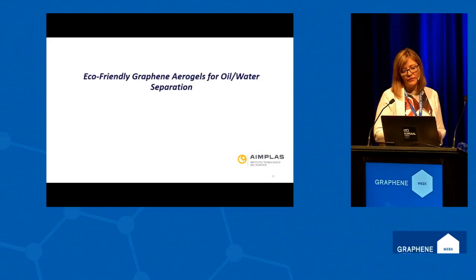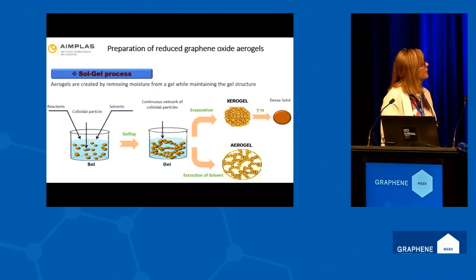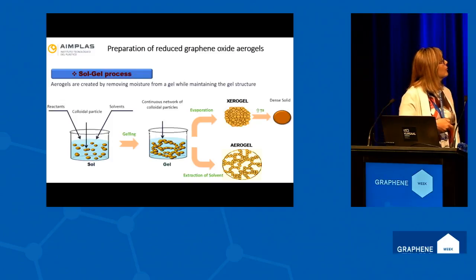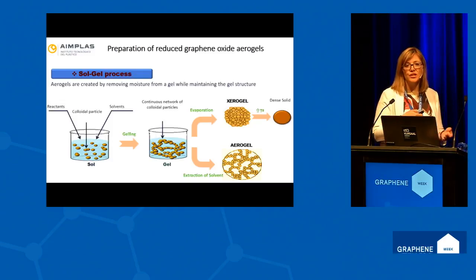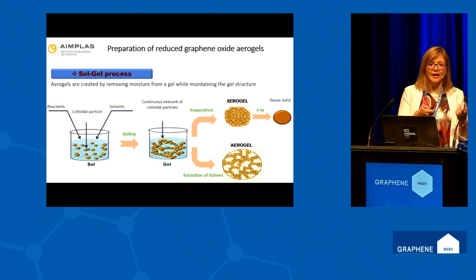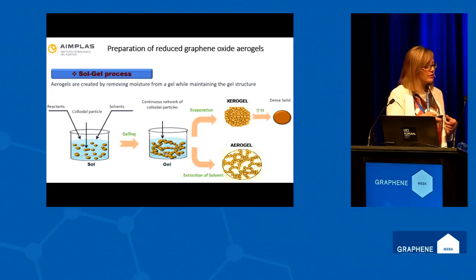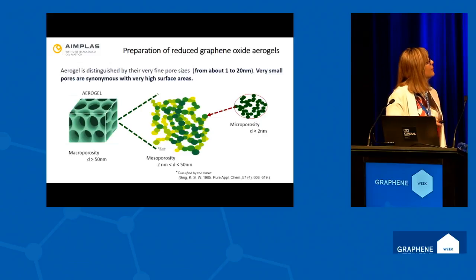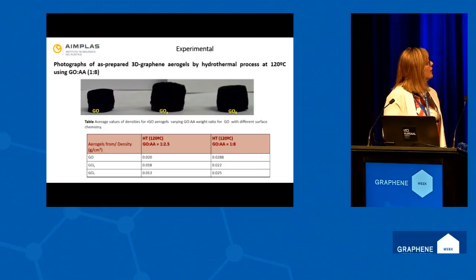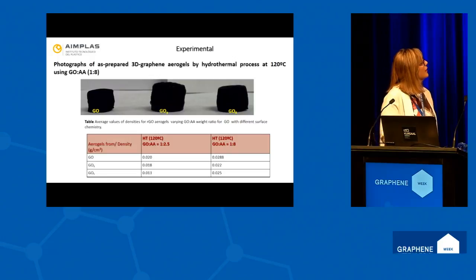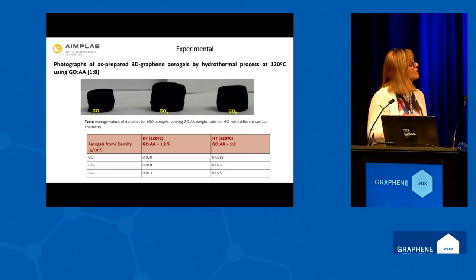And the other application that we have used in this project is to use graphene for oil water separation, very fast. Well, as you know, with aerogels you can modulate the structure, the porosity, the surface area, depending on how you obtain this aerogel, how you dry it and how you maintain the structure is very important. And well, the pore size is also very important to capture the substance that you want. And in that case, we have been studying different processing conditions and different combinations with ascorbic acid, and we have obtained very good properties.